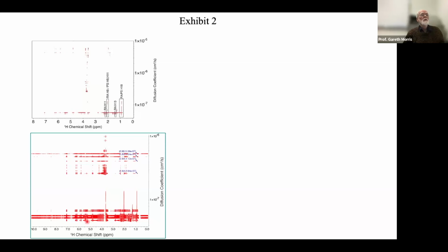If we look at an expansion, then sure enough, what we see is that the software is confidently telling us that we have identical, near identical spectra with similar but distinct diffusion coefficients. And this is a classic example of horrendous overfitting, that the software is being far too ambitious. And it's a black box, but it would appear that it's been programmed to recognize where peaks seem to have similar-ish diffusion coefficients and then nail them all down in a line. So not a nice thing to do.